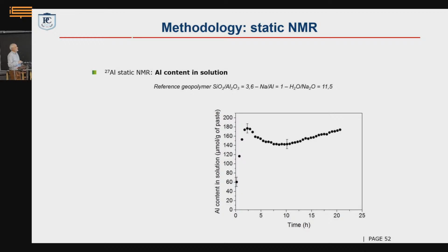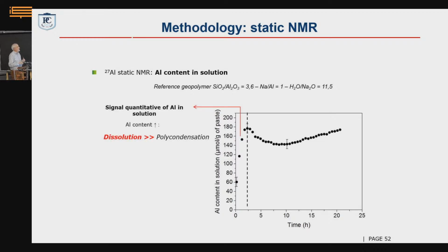So we are going to look at the aluminum in the liquid, not in the solid. And we look at the intensity of the signal that we calibrate somewhat artificially in terms of aluminum in solutions. We say as the aluminum-27 NMR signal goes up, that means there is more and more aluminum. This is true up to a certain level, and then life becomes more complicated for reasons I will try to explain briefly. But at the beginning, when you have just dissolution, you just release aluminate ions to the solution, and the signal is more or less quantitative. Once they start to polycondensate, life becomes more complicated. But at the beginning, when the system is dominated by the dissolution, we really have a reading here of how much aluminum goes into solution.